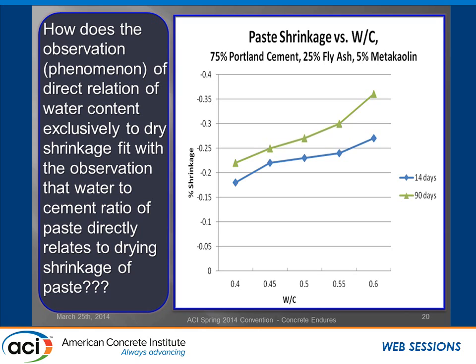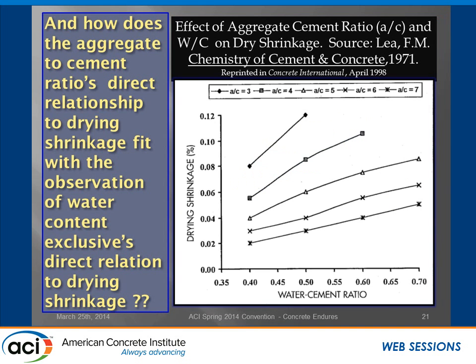These are actual shrinkage data here. This is Portland cement and fly ash and water and some metakaolin, and those are the cement, and that's shrinkage over about a 90-day period. Well, the blue one's 14 days as the water cement ratio changed. The top one's 90 days at each point with a different water cement ratio. There's nothing there that's surprising. Here we have a graph here. I'm going to get back to this one in a minute.